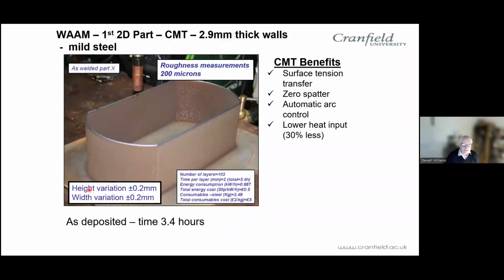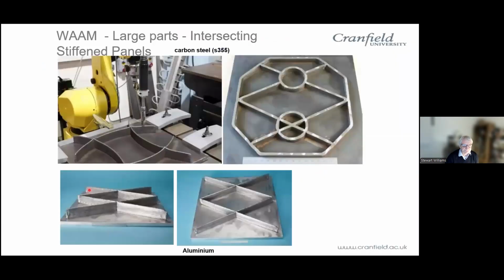When we first started, we used a particular process. There are many variations in processes, which I won't go into today. And we built this first part in an afternoon, took 3.5 hours. It was deposited rather nicely, and we thought, well, this is pretty good. Of course, it turned out to be much more complicated than we thought when we tried to make Class 1 engineering structures. So we spent a lot of time looking at the